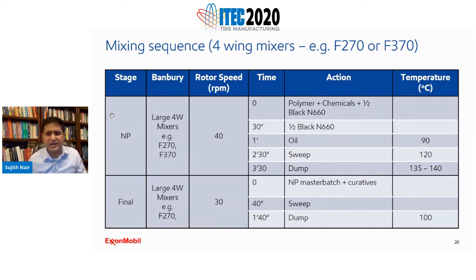we mix it for around 3.5 minutes. We normally go by the dump temperature. So we recommend a dump temperature of 135 to 140 degrees C for the non-productive batch and 100 for the final batch. But again, the reason why we picked 135, 140 is because this was what's used in bromobutyl. So we don't like to go above this temperature for bromobutyl.